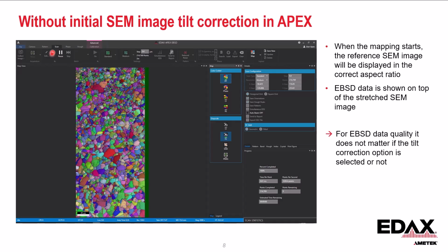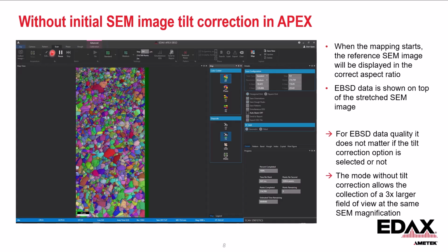So for the EBSD data collection itself, it doesn't matter if you switch this tilt correction in Apex on or off, the software will automatically apply the appropriate aspect ratio corrections. It's just that when you do not use the tilt correction, it will allow you a 3 times larger field of view at the same SEM magnification, which can be very helpful, for example, if you are measuring a thin coating on some substrate and you want as large as possible field of view.